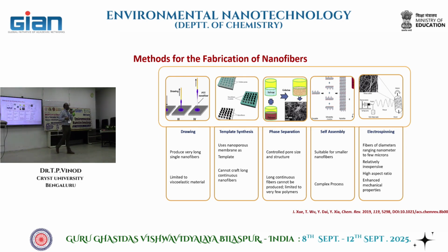If you want to make a cloth out of such fibers, you will use your entire lifetime to make it, right? Because only one fiber at a time you can prepare. It's a very slow process. Then you have template synthesis also, where you have patterned openings through which the solution is pulled down, and it comes out in the form of a nanofiber if the pores are nanoporous. Just like there are certain snacks we make, where you have some maida, atta or rice, and you push it through something and it comes out in different shapes, right? Similar to that, but in the nanoscale dimension.